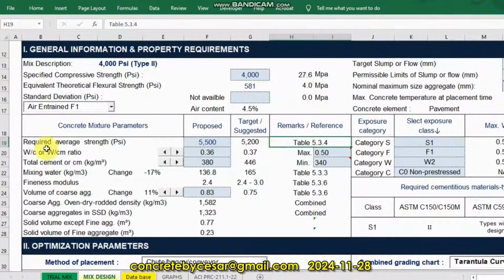So now going back to this required average strength or the target mean strength. As I've told you, this is the target or suggested strength with respect to the specified compressive strength. So simply they are saying if you need 4,000 psi minimum, at least you should have a margin to be on the safe side. So from 4,000 we have to target 5,200. We should design to get 5,200 psi at 28 days. That much margin is required so that we will be on the safe side.